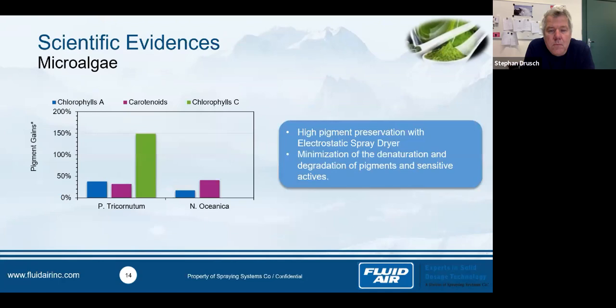Moreover, after that we checked the pigment gain, that means the more pigment that we have compared with a conventional spray dryer, and you can see with the chlorophyll A and the carotenoid, we increase by 30% the quantity of pigment. And in the case of chlorophyll C, we increase by 150%. So we really avoid denaturation and degradation. And we know moreover that we have this result because we work with nitrogen.